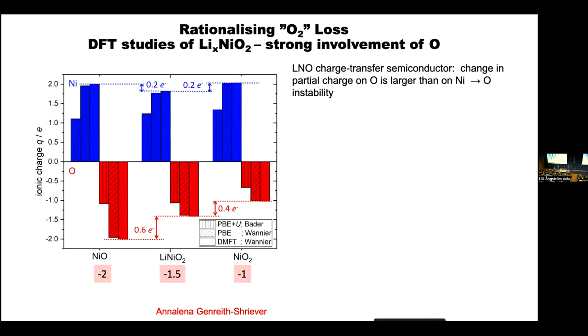This is work of Annalena, who's been doing a whole series of DFT calculations to look at the oxygen partial charges as a function of state of charge. And what she shows is that most of the action comes from the oxygen and not from the nickel. The nickel charges remain very similar from nickel oxide to NiO2. And what I'm saying is not an oxygen redox process. What I'm saying is the change of hybridization between the nickels and oxygens changes so dramatically between the formal 2+ state and the formal 4+ state that most of the action is on the oxygen.